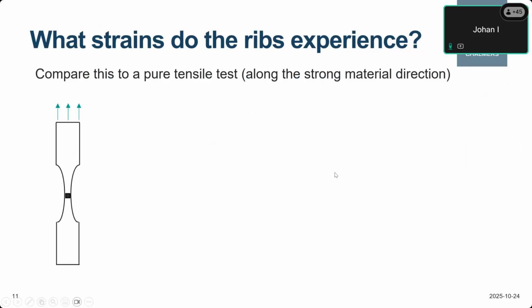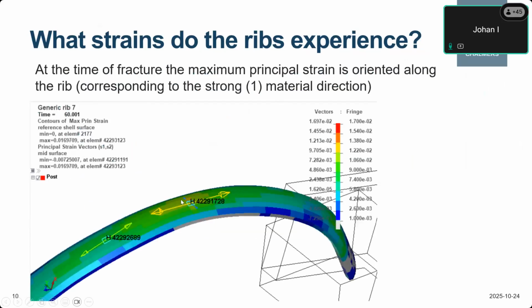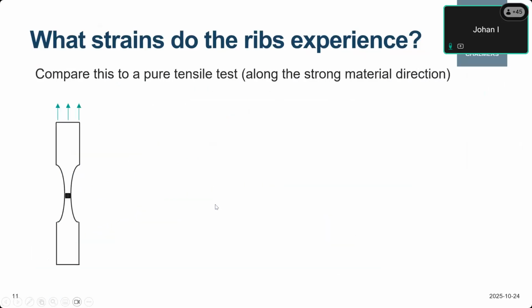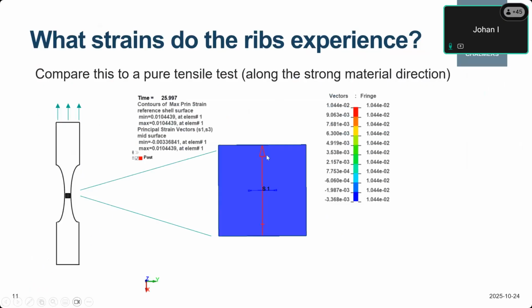So if I go up here, you can see that we have tension and then we have compression perpendicular. The compression here is due to the Poisson effect. So when we pull in one direction, the Poisson effect results in the material being pulled in the other direction. So the uniaxial tensile test here corresponds very well to the strain state that we have, at least in the anterior-posterior bending test.